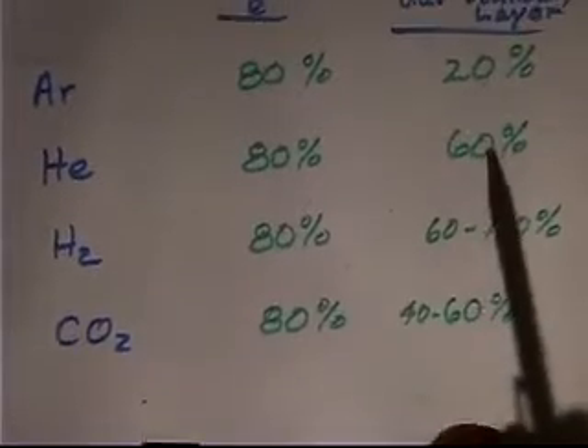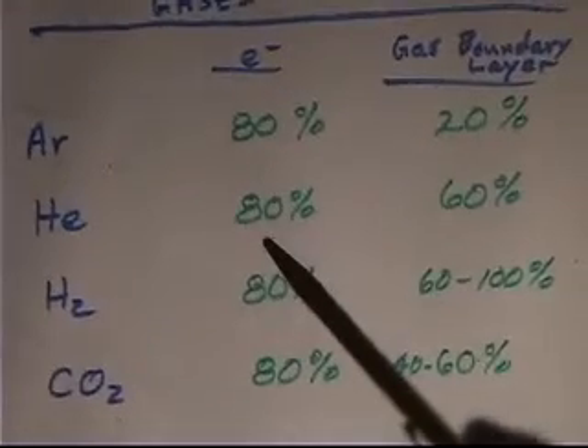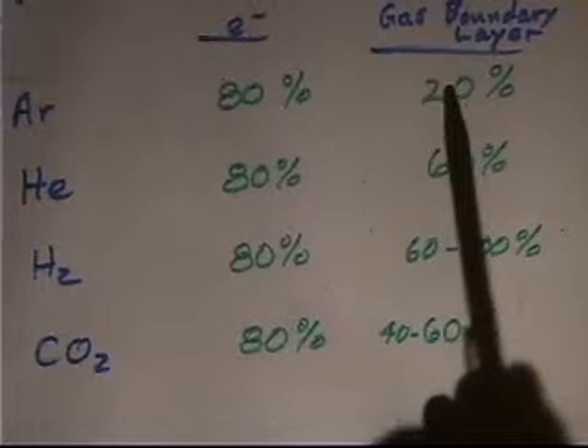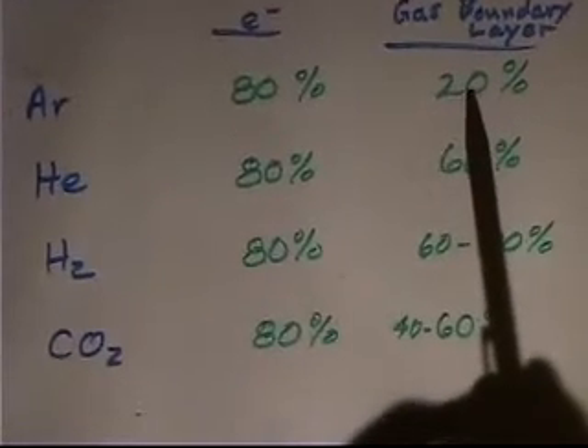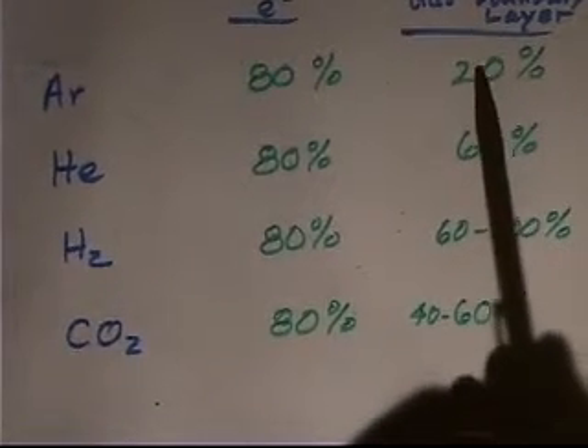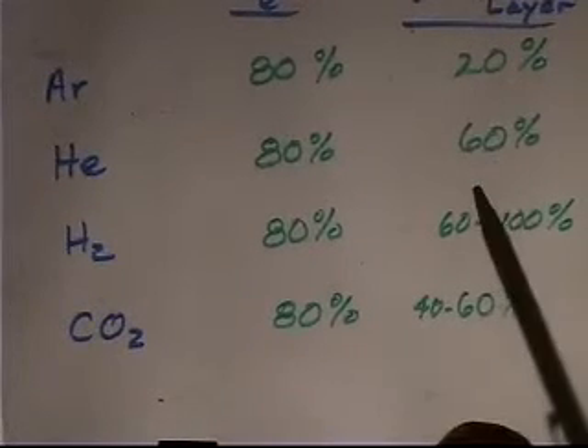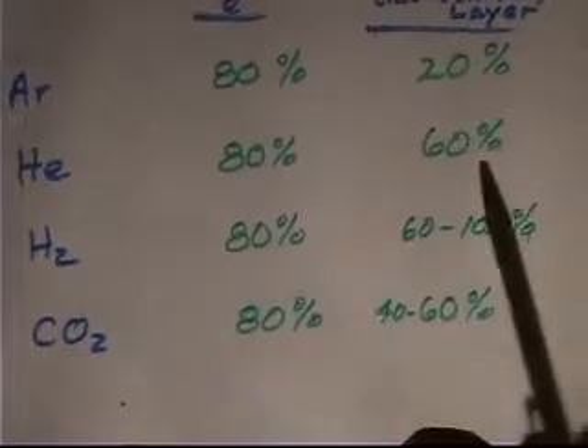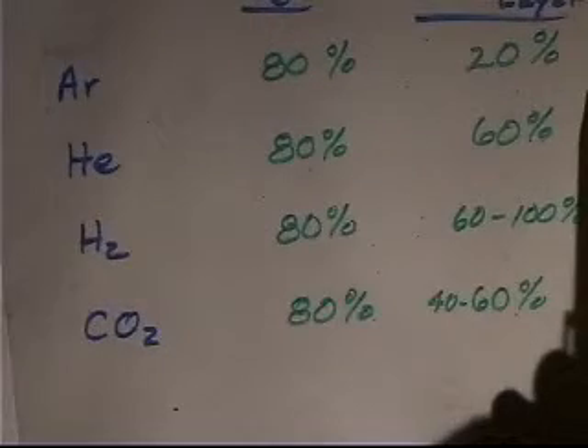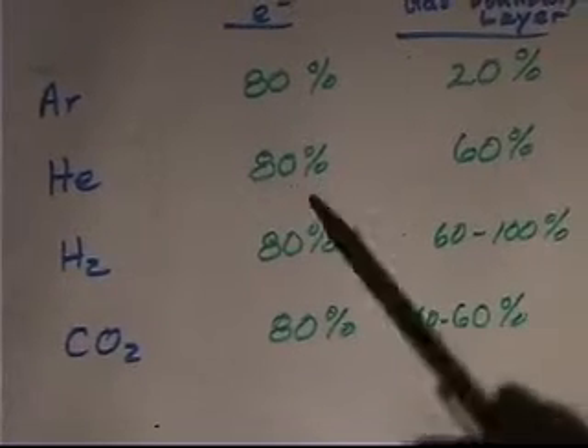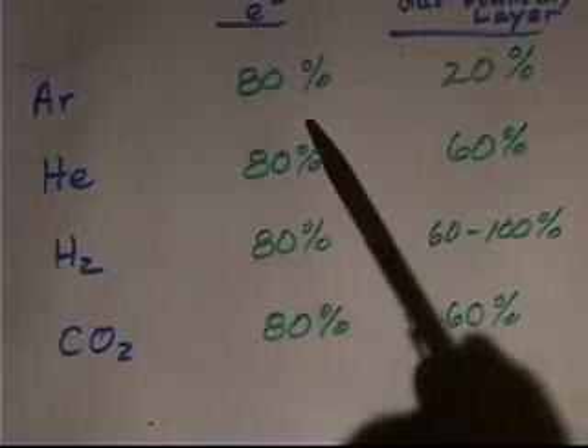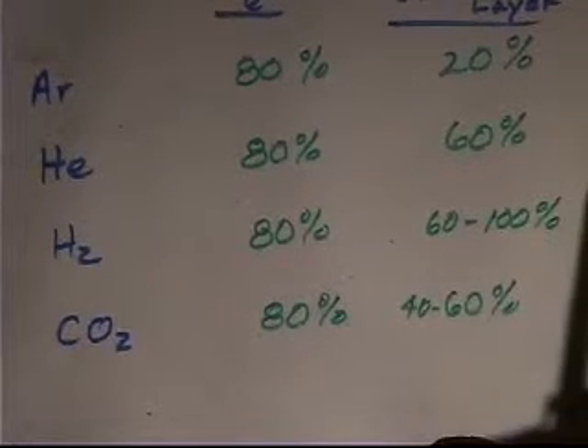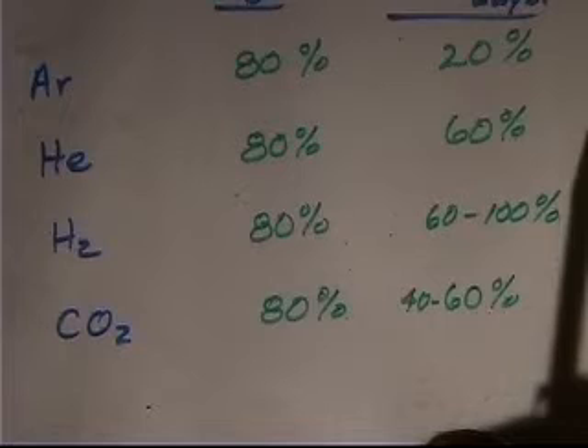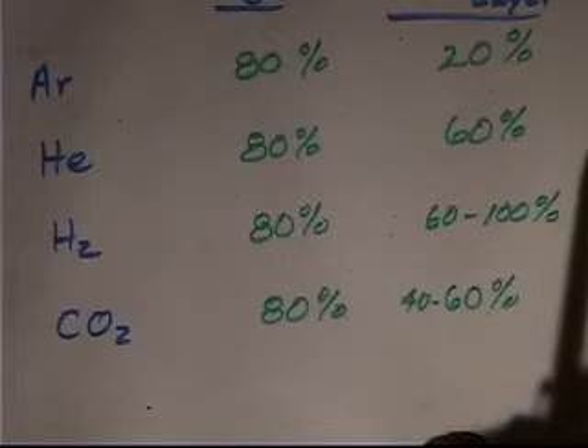That means, and since it's the thermal conductivity that controls the heat transfer across the boundary layer, if I'm going to get 80% of my heat from the electrons between a helium and an argon arc, I get 20% by conduction and convection across the gas boundary layer. With helium, I'll get 3 times as much. So the total here is 140% as opposed to 100%. I have a 40% increase in the heat transfer efficiency when I use helium as opposed to argon in welding. It has nothing to do with ionization potentials, in spite of the welding handbook and what it says.